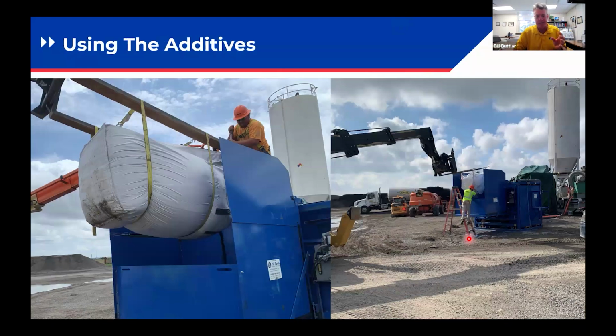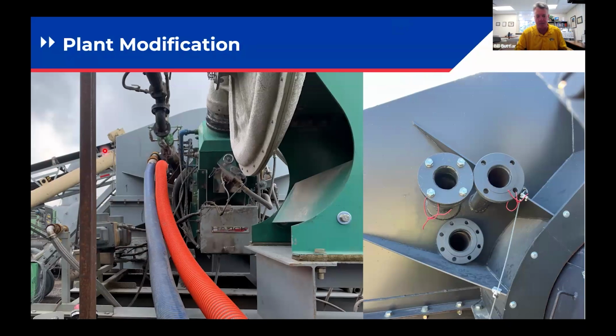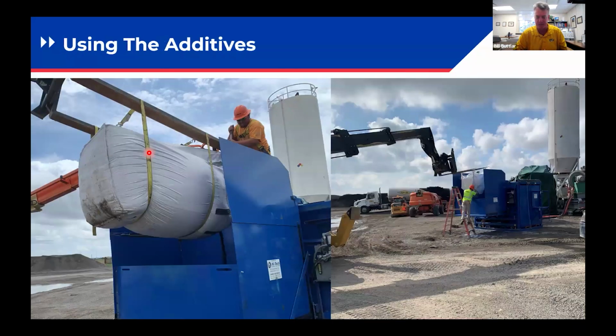And then you can see we're not feeding these additives in the wrap collar, which you could. This particular one had the asphalt coming in. It hits a deflector plate. It creates a fan of asphalt. And then you can inject the additives kind of hitting into that fan of asphalt so that it gets incorporated in the asphalt, and then it tumbles through the last part of the drum. So that's a good way we find to do that. You don't want materials ending up in the dust collection system any more than they have to. So firing the dry additives right into the asphalt is an effective strategy.